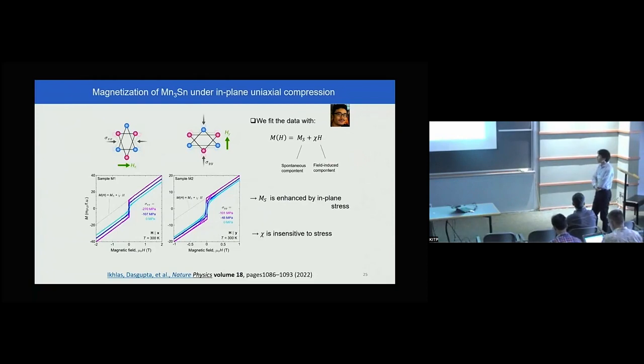Yeah, and that's actually quite interesting. Indeed, the magnetization, or the spin texture, is strongly coupled to this mode, and they can actually identify which mode is coupled to this elastic modulus, which shows a strong anomaly at the transition temperature, and it's consistent with this piezomagnetic effect. So the piezomagnetic effect seems to show up also in this ultrasound measurement.